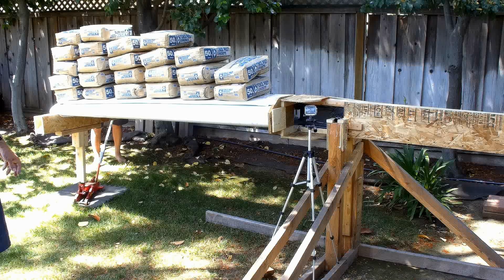Never ceases to amaze me what you can do with these composite materials. There we have a section of wing that weighs just 15 pounds carrying 1,200 pounds of load, and it would have gone even more if the test fixture had not failed. So pretty good design, solid for moving forward with, and now it's just a matter of refining the root fittings to try to get the weight reduced a little.